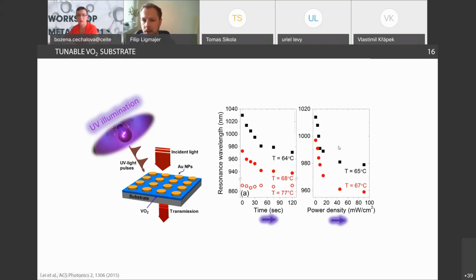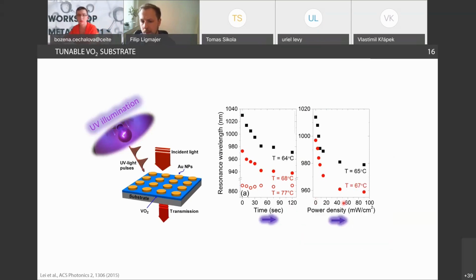And maybe let me start the laser pointer. If you basically latch the VO2 at temperatures close to its phase transition, even the small energy carried by the UV light can push your material through the phase transition. And what is nice is that this transition is then non-volatile. So unless you decrease the temperature, the VO2 stays latched in this half transition state and keeps like that even when you stop the UV illumination.